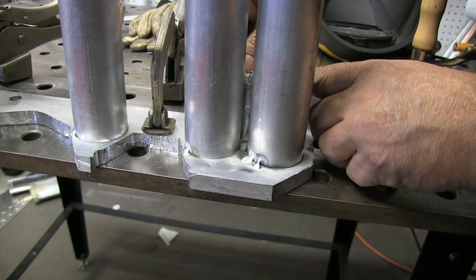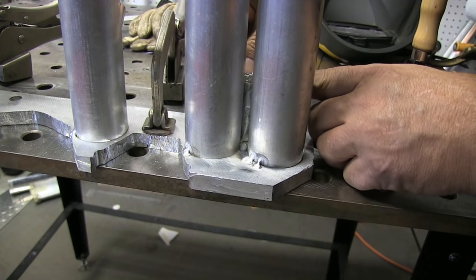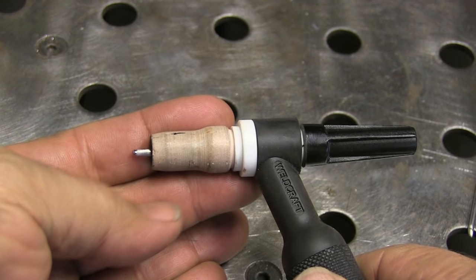These little areas here I'm going to have to extend the electrode a long way, I'm just making a quick dam of aluminum foil and the reason for the aluminum foil is because I'm gonna have to extend the electrode pretty far to get down in there and I'm gonna need all the help I can with argon coverage and so that'll just provide a little dam to keep the argon from flowing over and screwing up.